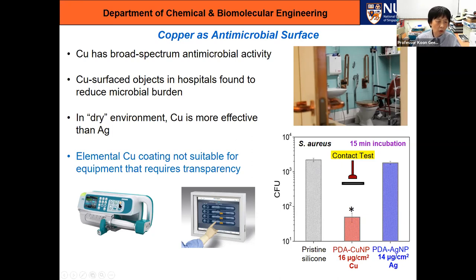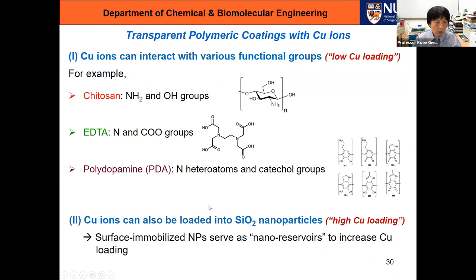So we know that copper would be a good thing to try, but because the request is for coatings over the instrument, we cannot use elemental copper like this because then they wouldn't be able to see the readings. So then we decided to use copper ions. So how do we then get the copper ions to stick to the surface of polymer sheets? So the first method we tried was, okay, we'll use certain polymers that have functional groups that the copper ions can interact with, like NH2 groups, OH groups, and so on.